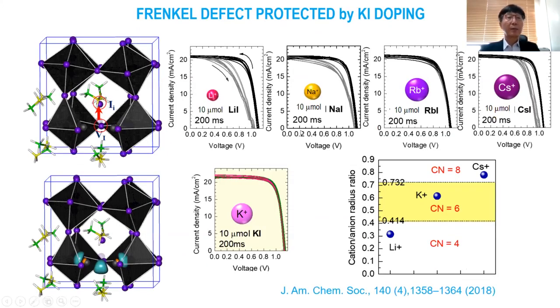We recently found that the perovskite undergoes a Frenkel defect. To protect against the Frenkel defect, if you include a small-size alkali metal ion such as potassium ion into the interstitial site, then you can effectively protect against the Frenkel defect. Therefore, you cannot see any pronounced hysteresis here.